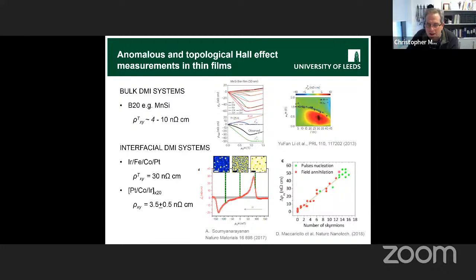This experiment was done by Vincent Cros's group in Palaiseau, and they also did MFM. They would count how many Skyrmions they had in their Hall cross, and they would measure the Hall signal. And what they found was, the more Skyrmions, the more Hall signal you had, more or less a straight line. But they said they could account for all of this signal, about 3 nano-ohm centimeters for every Skyrmion, just from the anomalous Hall effect from the reverse magnetization. And there's no topological part, whereas here, everything else has been subtracted out. So this is topological or something else you haven't thought of. So there's a discrepancy between these two experiments as to what you're really measuring when you get these signals.